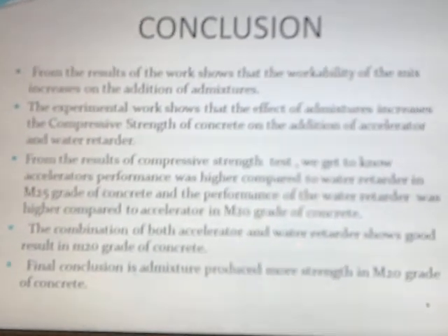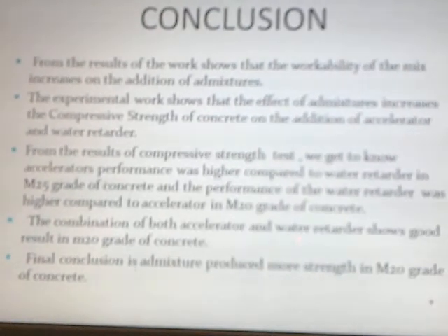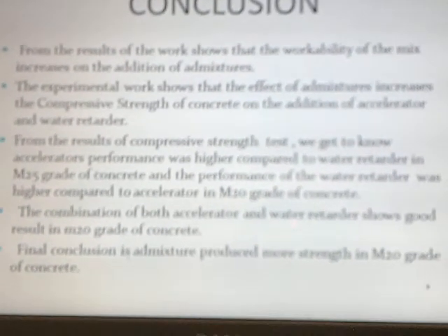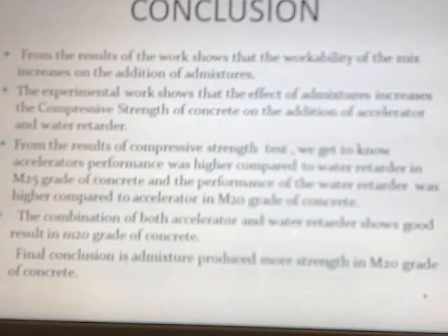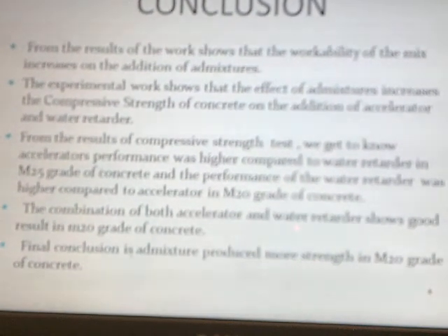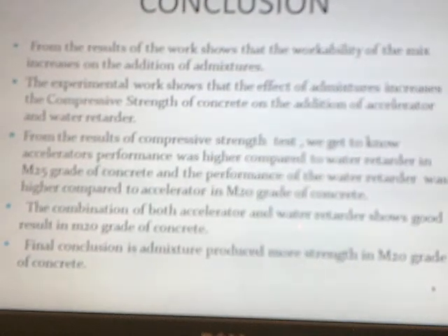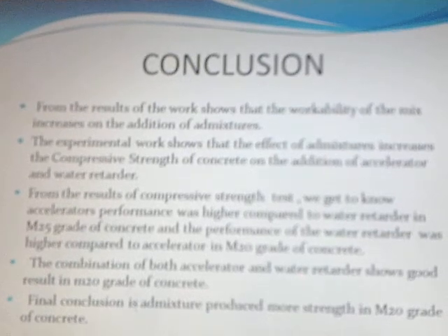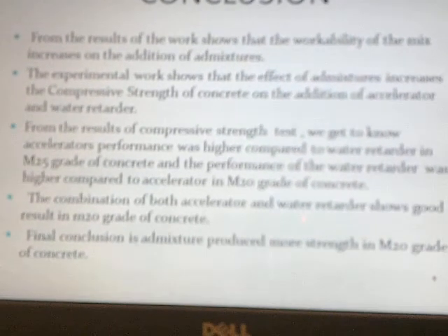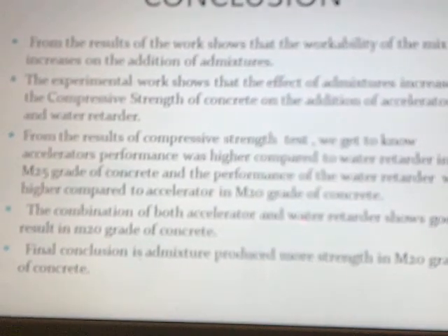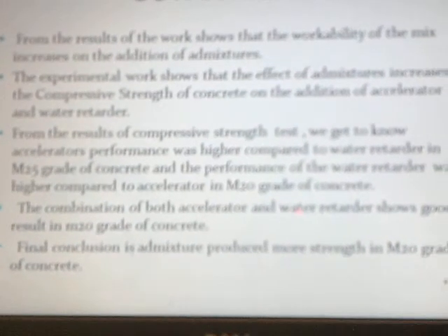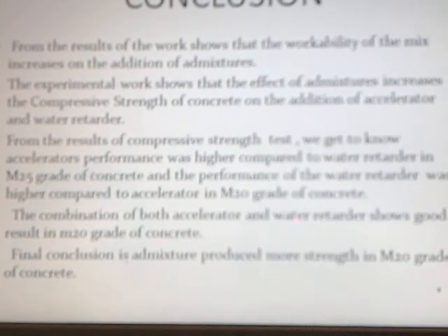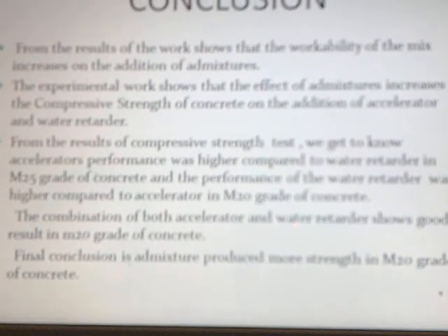Thus we conclude from the results of the work that the workability of the mix increases on the addition of the admixtures, and the experimental work shows that the admixtures increase the compressive strength of the concrete on the addition of the accelerator and the water retarder. From the result of the compressive strength test, we get to know that the accelerator performance was higher compared to the water retarder in M25 grade of concrete, and the performance of the water retarder was higher compared to the accelerator in M20 grade of concrete. The combination of both accelerator and the water retarder shows good results in M20 grade of concrete. Final conclusion is that the admixtures produced more strength in M20 grade of concrete.